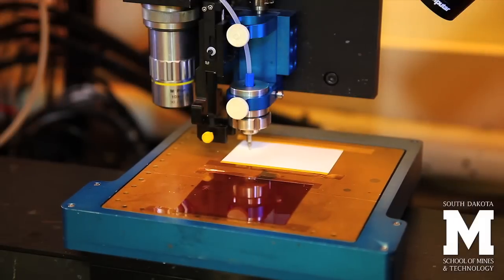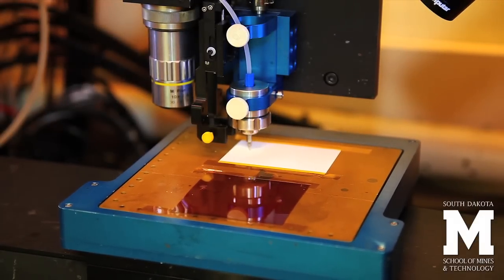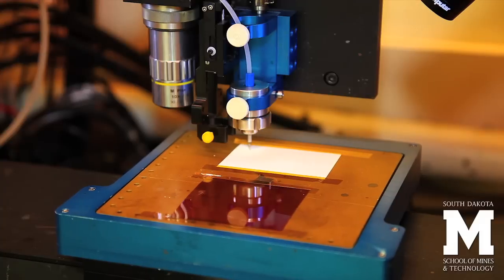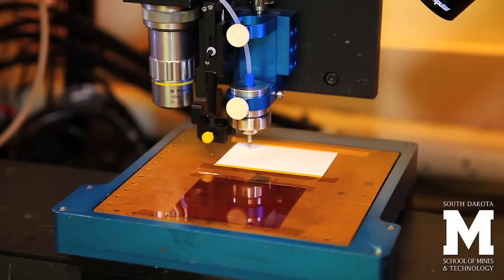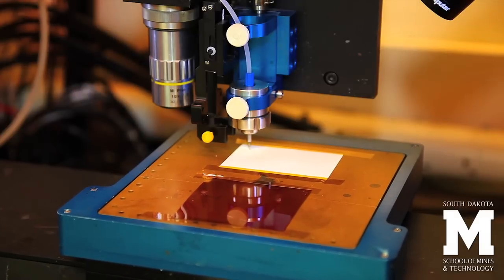Once we give the atomizer flow value, it takes the ink from the vial to the head through the pipe. Then once we give the sheath, it prints the ink onto the substrate. So far we have successfully printed lines of about 50 microns with the control parameters.